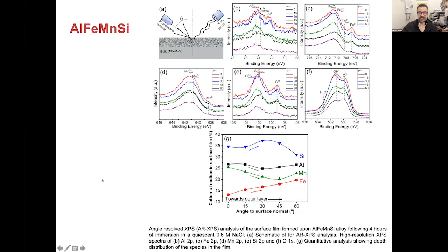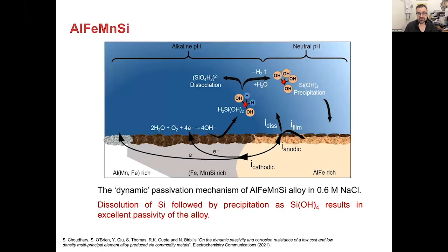And so nothing tells a story like a good cartoon. So in this particular cartoon, this shows the mechanism by which corrosion resistance is imparted to this alloy. It's a dynamic passivation that actually happens by a small amount of dissolution promoting silicon loss, so silicon dissolution, which is then followed by precipitation as SiOH4, which is a common product from the dissolution of silicon dioxide in the presence of water as well. And it's this particular phase in the surface film that provides excellent passivity of this alloy too. So it's a different way of thinking about passivity. Dynamic passivity, kinetics are important. And clearly we're getting to understand these particular alloys in ways that we couldn't previously because of methods like spectroelectrochemistry.